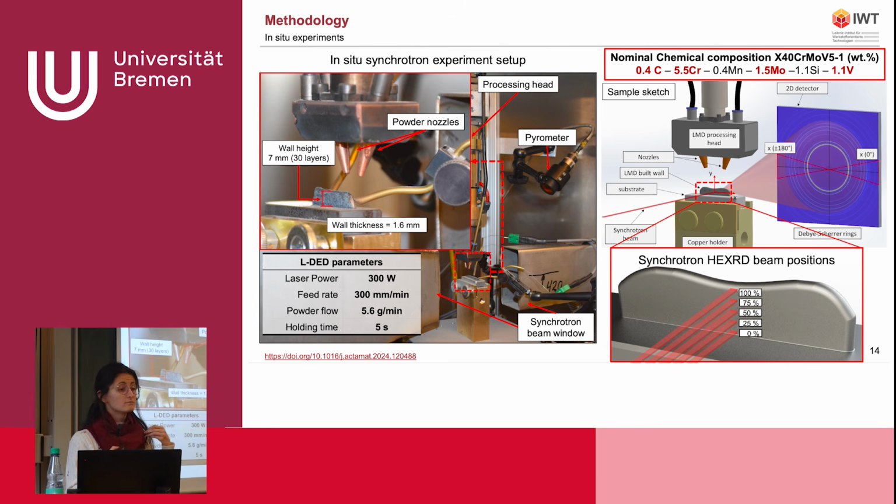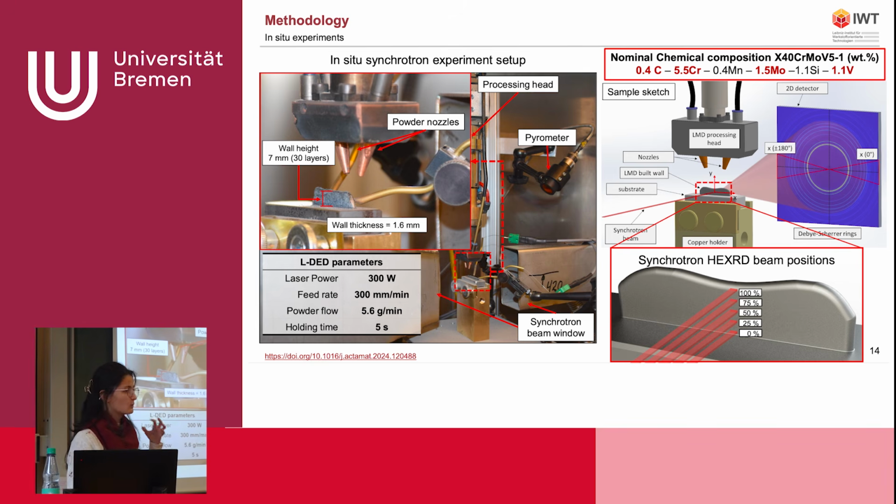So we have the theoretical stoichiometry and which type of metallic elements they might, for example, contain. For chromium carbides, we know that it must be chromium with carbon, but with substitutional elements such as iron, which is the main element here. We don't know if it would be pure chromium or pure iron or a mix of it, and so this would give us information about how far we are from equilibrium.